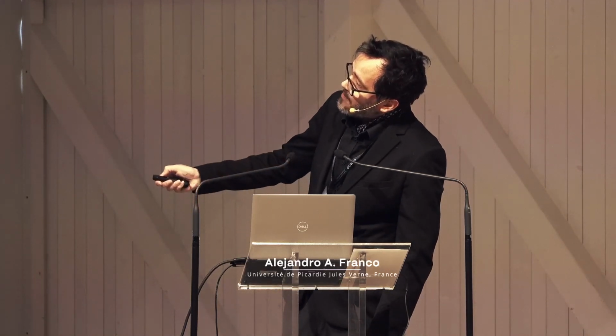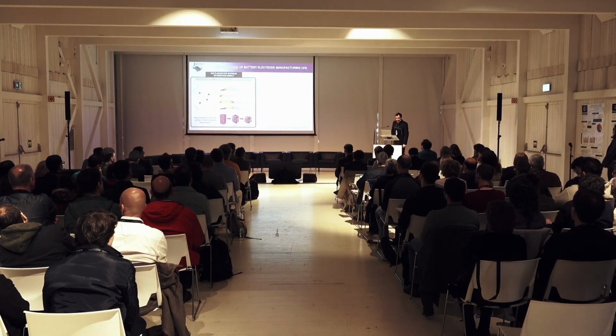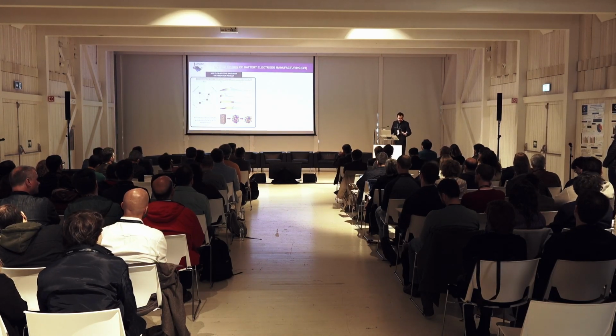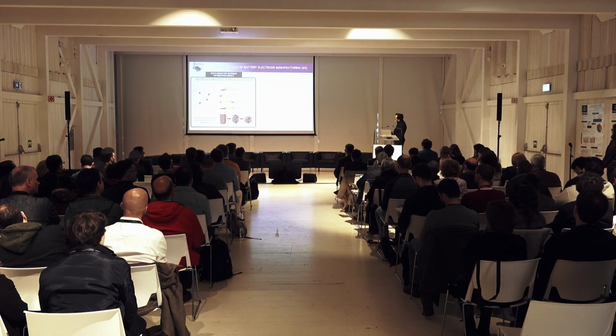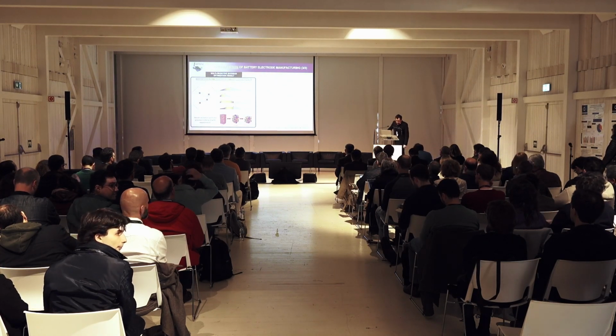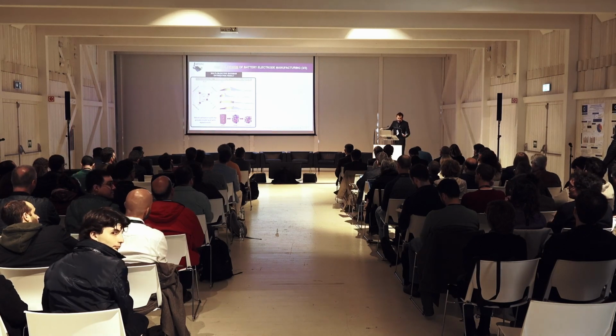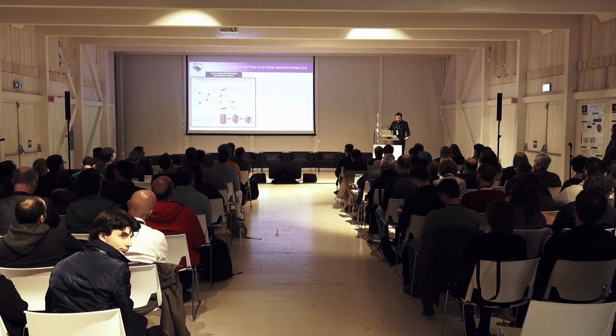And then by embedding these manufacturing parameter values into our physics-based manufacturing simulator, and when we predict the electrode microstructures thanks to this simulator and characterize the properties of these electrodes, we realize that the properties predicted match very well with the prediction arising from Bayesian optimization. This is a way of validating the outcome of the surrogate model based on machine learning plus Bayesian optimization. And then we perform experiments on top of that to validate further, and we found that it was matching very well the experimental data that we had.